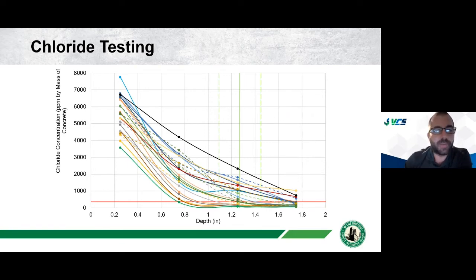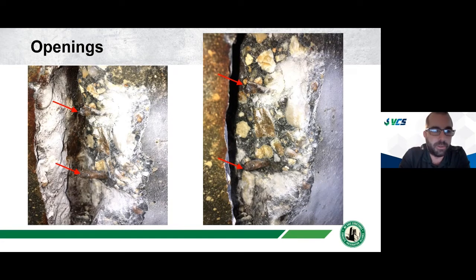And so we did some openings to inspect the steel at the cracks. And lo and behold, my suspicion was correct. The steel that crossed those cracks was 100% gone. Because those cracks were open, allowing salt water to wash in and out of those cracks, it allowed for corrosion of the steel, but the iron oxide was washing away, so it never built up enough iron oxide to cause a spall or a delamination. And so at each one of those cracks, you then have lost 100% of your strand of your spiral reinforcement. So obviously this is a very concerning situation. Based on that investigation, they've started doing repairs on that structure.